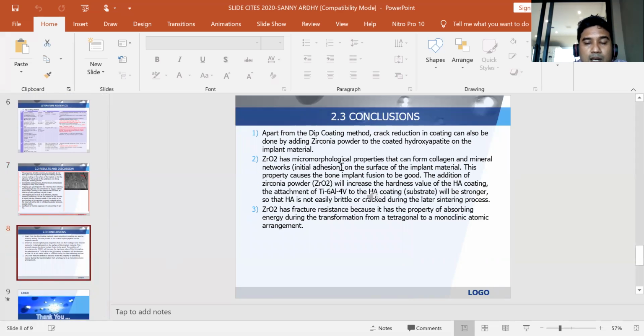The conclusions of my paper are, apart from the dip coating method, crack reduction in coating can also be done by adding zirconia powder to the coated hydroxyapatite on the implant material. Zirconium oxide has micromorphological properties that can form collagen and mineral networks for initial adhesion on the surface of the implant material. This property causes the bone implant fusion to be good.